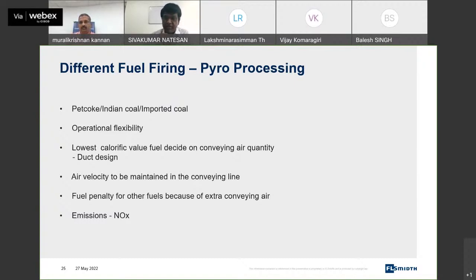So if you have a conveying system for this type of arrangement where multiple fuels can be used, the conveying air quantity is dictated by one of the fuels. For example, if you see pet coke, Indian coal or imported coal, Indian coal tonnage will be maximum for the same heat consumption. So the tonnage will dictate how much conveying air is required and what the size of the conveying pipe will be. Even though you have a variable speed for making the conveying air variable, the pipe size, whatever you select, needs to have a minimum velocity maintained to avoid coal fluctuation. So when you design it based on high tonnage, based on Indian coal, your pipe size will be large to take care of that tonnage.